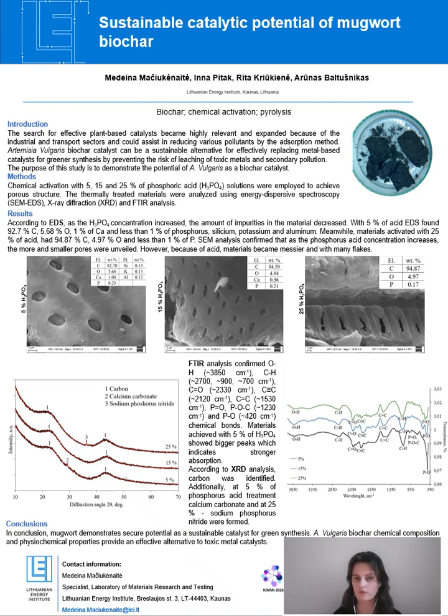So to achieve porous structure and gain the materials without compounds which could disrupt the effectiveness, chemical activation with 5, 15, and 25% of phosphoric acid solutions were employed. Then thermal activation of treated materials was utilized under nitrogen atmosphere at 850 degrees Celsius to achieve unveiled pores. Obtained biocarbon was analyzed using scanning electron microscopy coupled with energy dispersive spectroscopy, and this equipment analyzed the surface morphology and elemental composition. X-ray diffraction analysis was conducted to investigate the crystalline structure and composition, and I used also FTIR, Fourier transform infrared spectroscopy, and it was performed to identify the functional groups present on the surface.